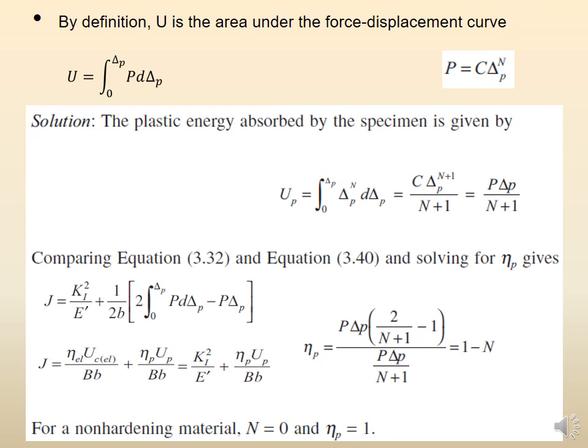So this one example, see in this way the book is very good. Some of the theory, rather than developing as theory, they give you as an exercise. And then you apply the previous equations and now you found that eta_P for DENT equals 1-N. And this 1-N reduces to only one if it is a non-hardening material.